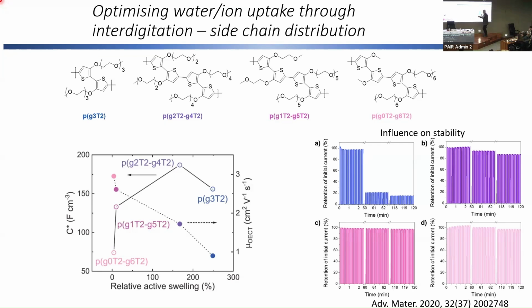So we have a very short chain followed by a very long chain. This allows interdigitation, and when we get interdigitation, we get a very small amount of swelling. So relative swelling is small, and in this case our carrier mobilities are large, but our volumetric capacitance is low. So again, you see that typically we trade off mobility and volumetric capacitance, and we reach a point where you get this sort of volcano-type plot, with a maximum somewhere in the middle.